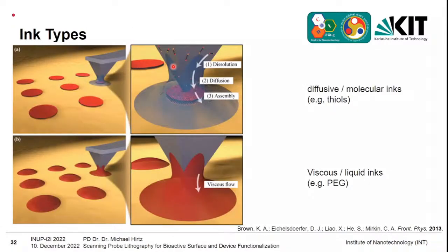So yeah, now the thiols are not the only ink type that can be used in dip-pen nanolithography. It can also be other things than thiols, and as long as they still go over such a diffusion process, we usually call them diffusive or molecular inks. And this works like I just described, that you have a dissolution from the surface of the tip into the water meniscus and assembly on the surface. And you usually end up then in these kinds of self-assembled monolayers that are highly localized on your substrate.